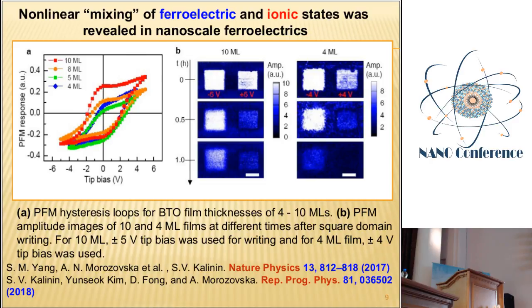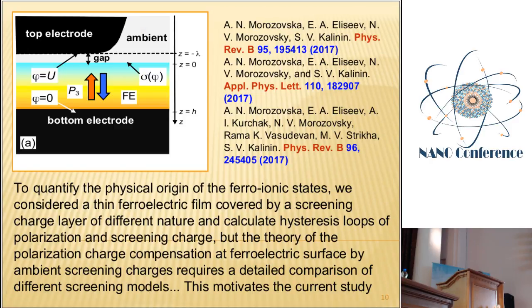Well, how in principle can we quantify all these results and understand which screening is required for a concrete case? We should consider a system which contains a bottom electrode and a ferroelectric film, with or without domain structure. It should be considered self-consistently. Does this structure form or not under a certain condition? A layer of the screening charge covers the top surface of the film, and the electrode. The electrode can be plain or tip, it can be remote or very close. So we should have the possibility to vary the thickness of the gap between the film and the top electrode.